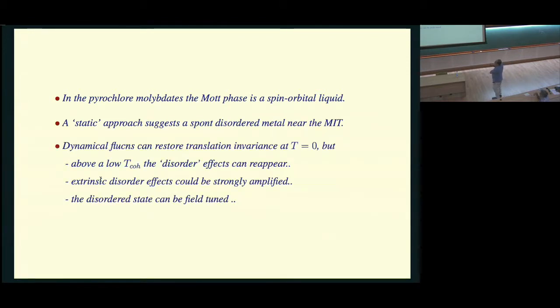However, what one can argue is that even if translation invariance is restored below a certain coherence temperature, it's possible that above that coherence temperature, these quote-unquote disorder effects still come back into the story to give you an unusual resistivity. Extrinsic disorder, which is inevitable in most of these materials, is likely to break the coherence and bring down the coherence scale, and again lead you back to the kind of phenomena you're seeing here. And of course, the disordered state, both in the theory and the experiment, can be field tuned. So the disorder, even if you could push it out through quantum tunneling processes, would resurface at finite temperature or be promoted by disorder, but then be annealed by an applied field. So that is the story. Thank you.